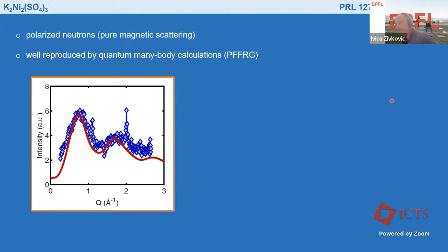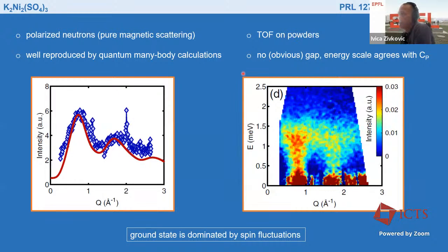And then further on this dynamic part, we also did polarized neutrons, where you pick up only magnetic scattering, and that behavior is rather oscillatory. You don't have peaks appearing, and this behavior can be reproduced rather well with quantum many-body calculations, which I think have been lectured here by Johannes Reuther previously. And also, if you do time of flight neutron scattering on powders, you obtain this result with no obvious gaps appearing at low energies, and an energy scale which agrees with both the results of specific heat and the Debye temperature.